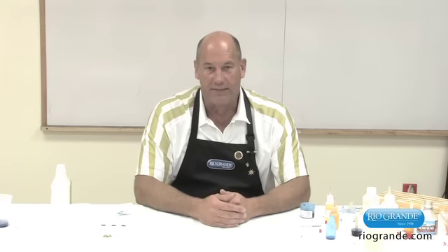When using ColorEase Epoxy Resin, the only problems you're likely to encounter are two. The most obvious one is overfilling. If the resin runs out of the object that you're coloring, chances are you simply applied too much resin. You can wipe that area clean with a cloth or towel, removing the resin, and refill it with a fresh batch. The other problem you're likely to encounter is bubbles.